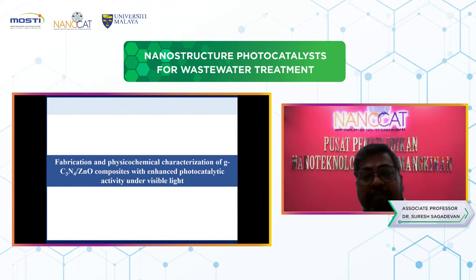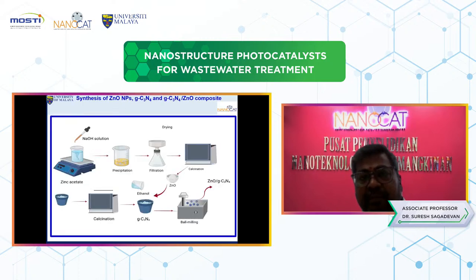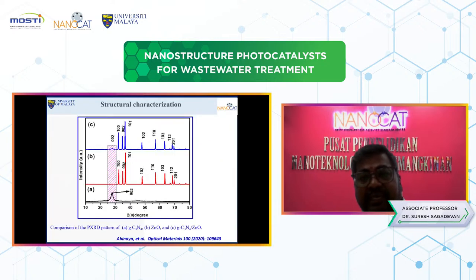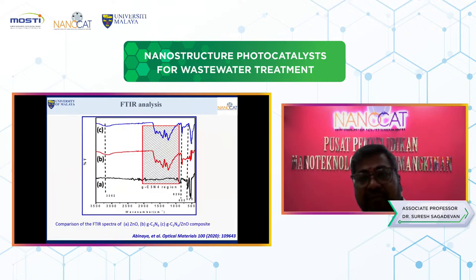And then finally, the next material is the g-C3N4 with zinc oxide nanocomposite with enhanced photocatalytic activity under visible light. We prepared it by simple ball milling, with the nano zinc oxide prepared by a chemical method and then the composite prepared by the ball milling technique. You can look here at the XRD pattern of this composite. In the composite XRD pattern, you can see both sets of planes are present, like zinc oxide and the composite peaks, which means the successful formation of this composite is confirmed from the XRD analysis and as well as the FTIR.